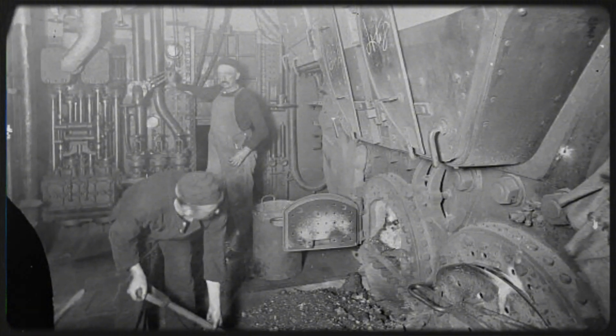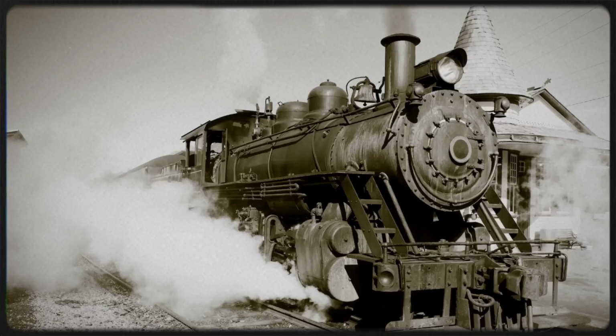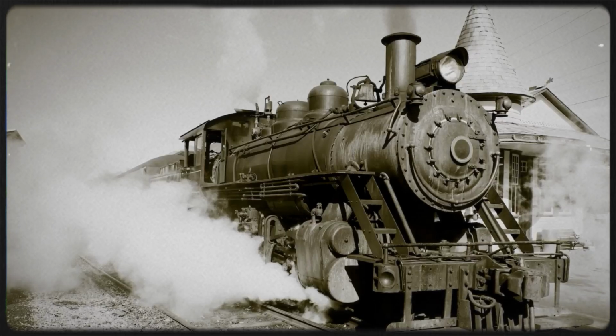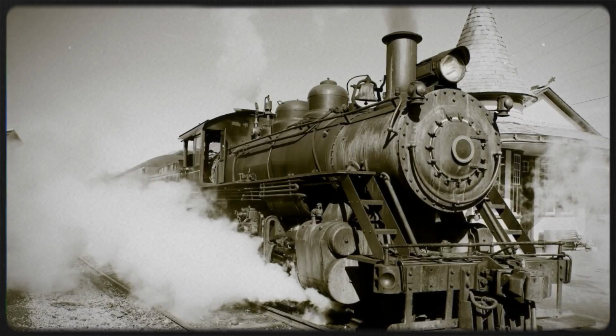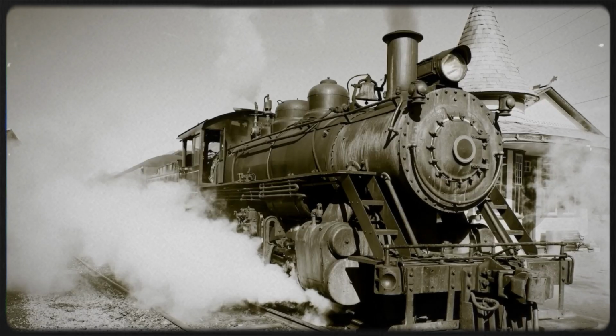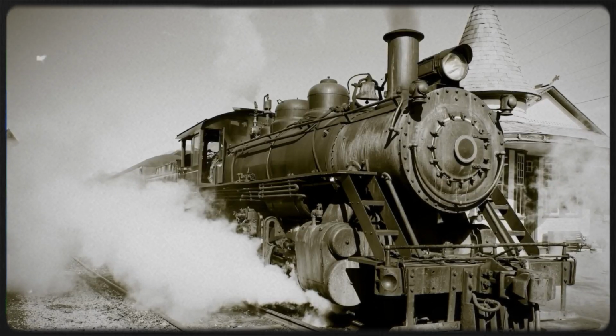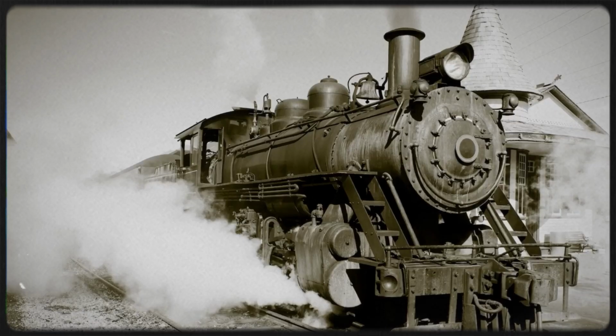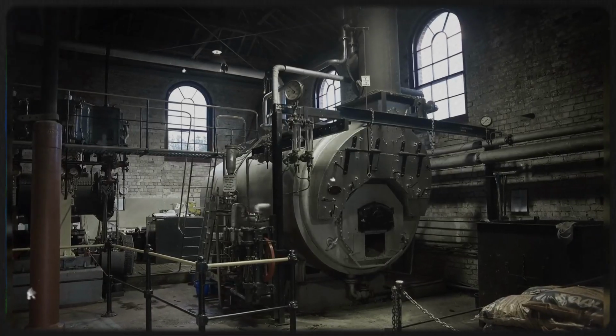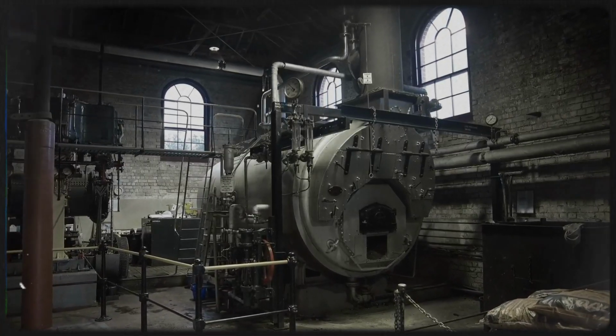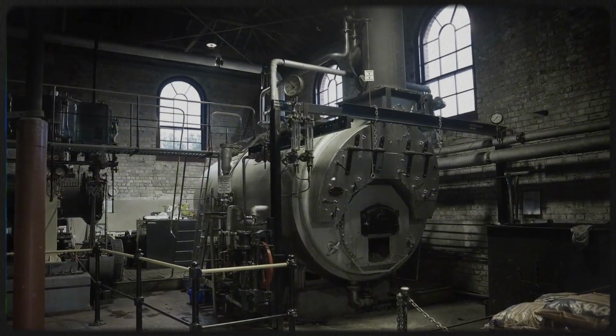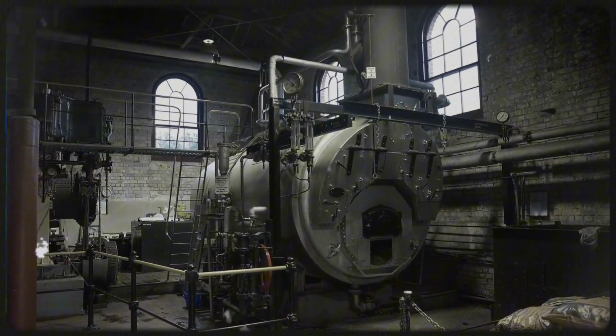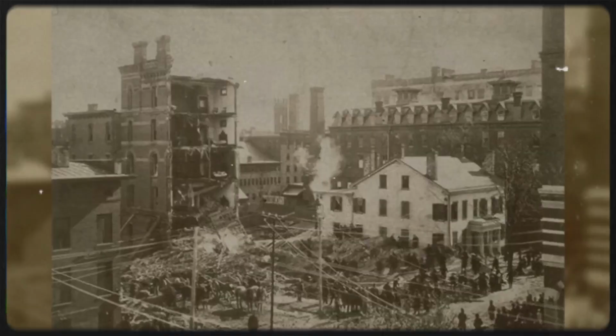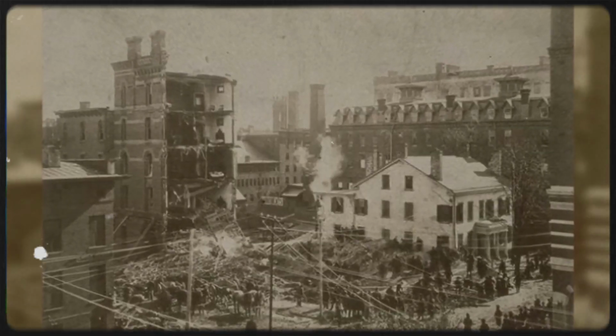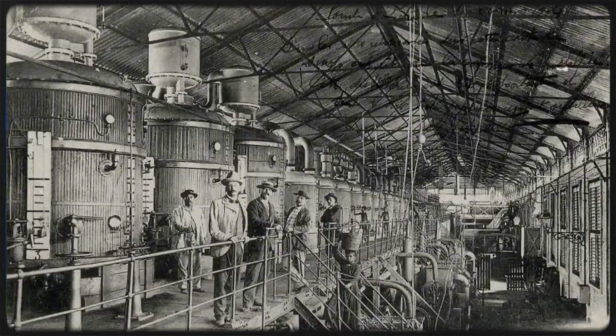But when the water level in a boiler drops too low, sections of the metal wall are exposed, no longer in contact with water on the inside. Those exposed sections heat up rapidly. The metal begins to soften. Its ability to contain pressure drops, and then, if cold water suddenly contacts that overheated metal, whether because a panicked operator tries to refill the boiler or simply because the water sloshes, the thermal shock can cause an immediate violent failure. There is another mechanism at work here too.